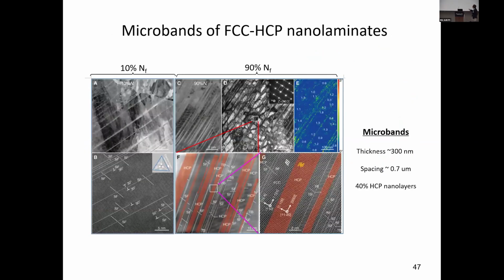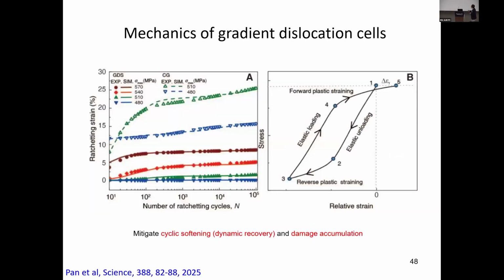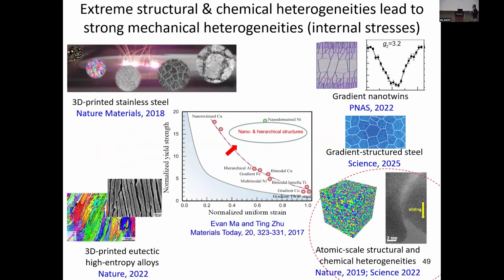So we also discovered the new deformation mechanisms due to this phase transformation during the deformation from FCC to HCP phase transformation, forming the nanolamellar microstructure that was not observed in conventional 304 under the cyclic loading. And we also understand this internal stress evolution to predict their ratcheting response to compare with the experimental measurement. This shows the importance of understanding this internal stresses to further push the limit of their mechanical behavior.